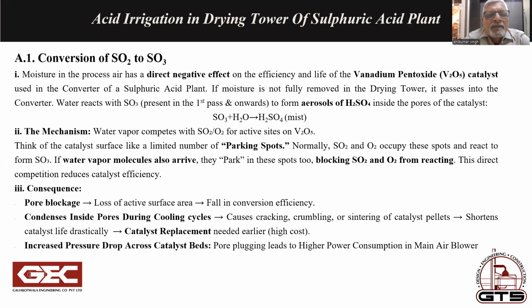Think of the catalyst surface like a limited number of parking spots. Normally, SO2 and O2 occupy these spots and react to form SO3. If water vapor molecules also arrive, they park in these spots too, blocking SO2 and O2 from reacting. The direct competition reduces catalyst efficiency.